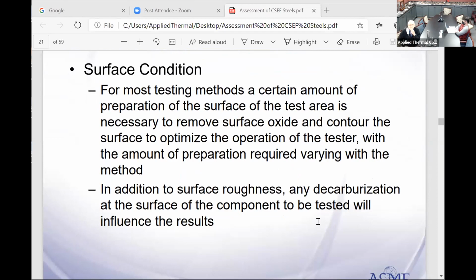So yes, for most testing methods, a certain amount of surface preparation is required to remove the surface oxide and improve the surface roughness. Decarburization is a big issue, and all you're getting, as you know, on these portable hardness testers is just this surface hardness.